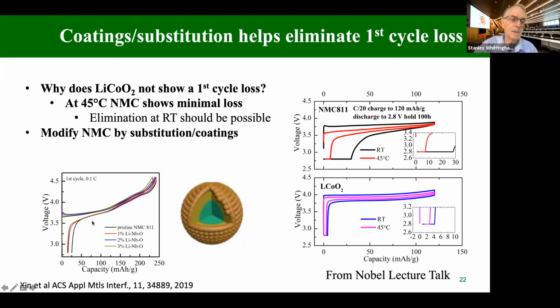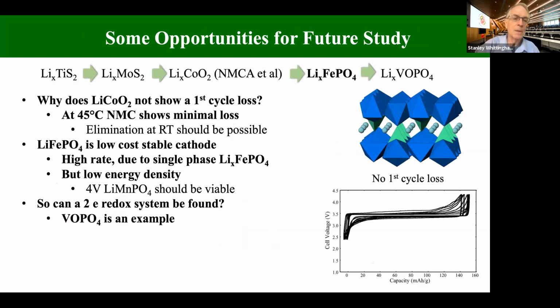And you can see now here, the black line is pristine material, no niobium, and putting 1% or 3% in cut this by about 40%. So just 1% does the trick. We're now trying to get it so it goes all the way back to the original. So we think it's possible to eliminate this first cycle loss. This will let us get the capacity still higher, and does it at a voltage regime where the electrolyte is not threatened by decomposition. So let's look at some opportunities for future studies.